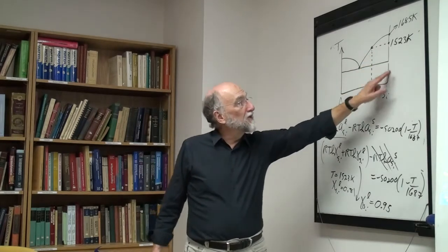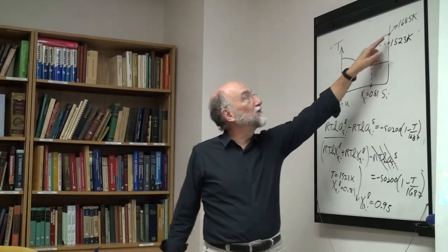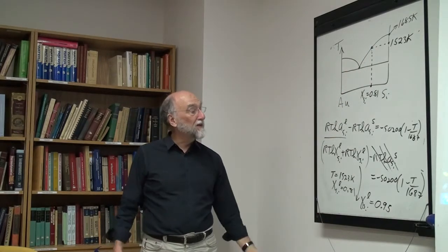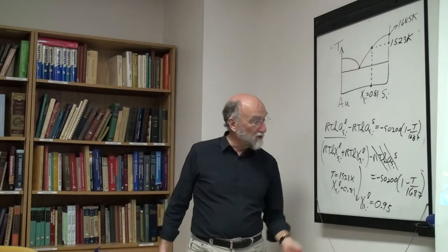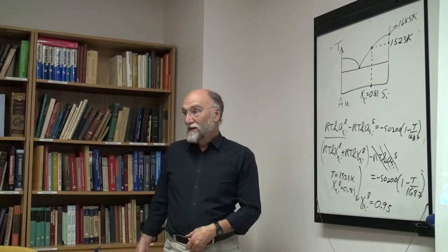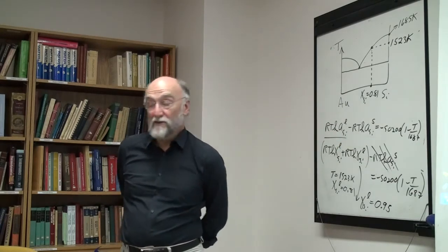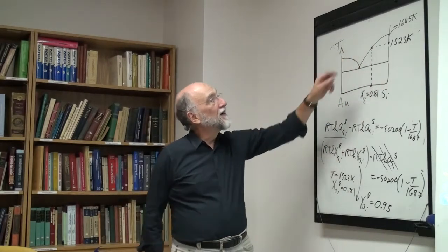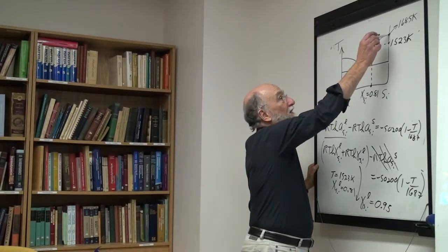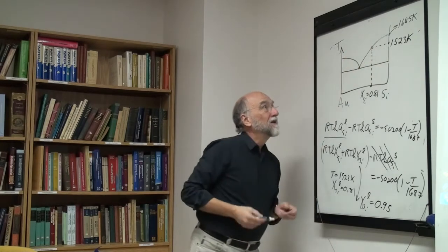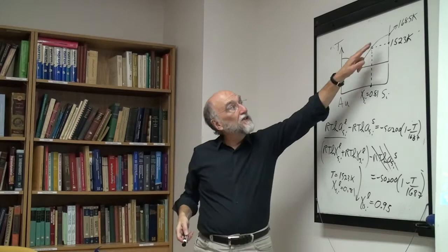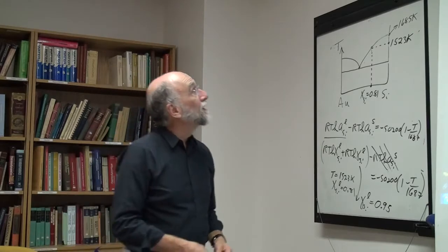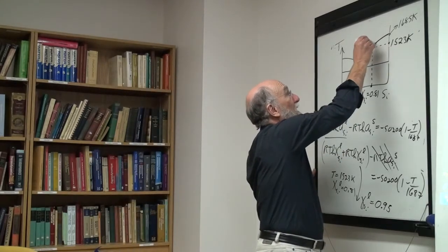If you have very little solid solubility, then the phase diagram actually gives you the activity coefficient in the liquid. It's exact, there's no modeling here. I'm not assuming a regular solution or anything, I'm just calculating it for the liquid, and I'm calculating the excess Gibbs energy, or the same thing. So that's why, when you have very little solid solubility, the important thing, for calculating the phase diagram, is what I need to calculate for this liquid. This is important and it's missed when you're using the computer. It's missed a lot by CALPHAD people too.